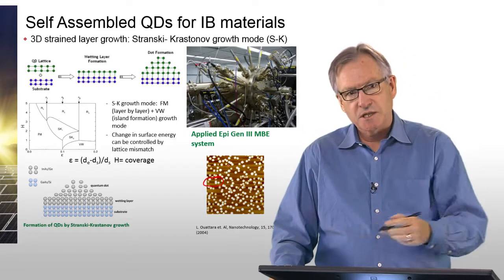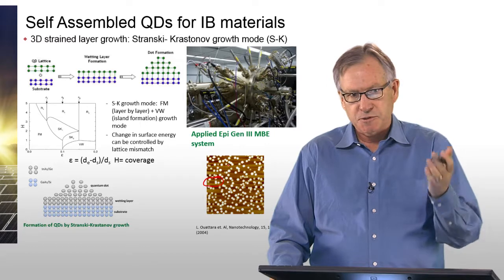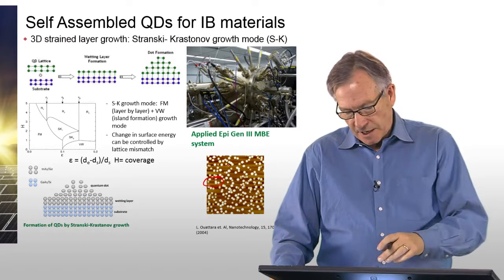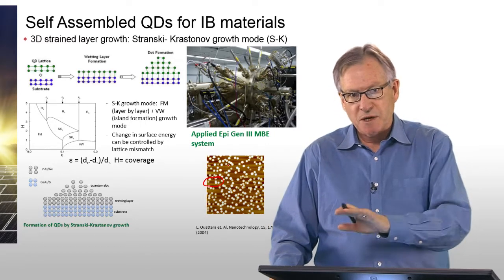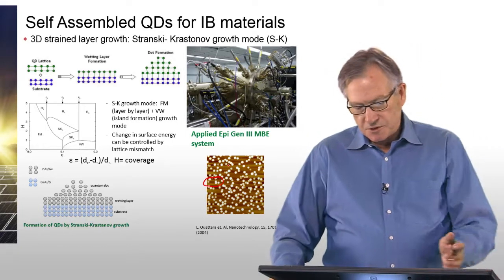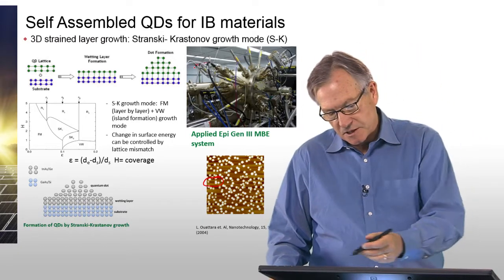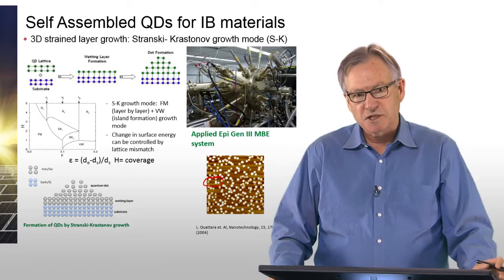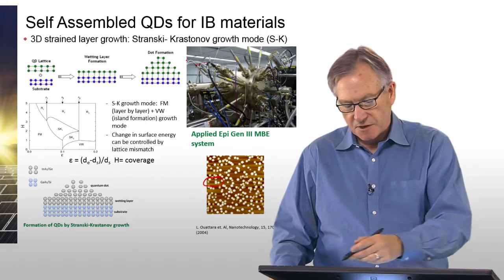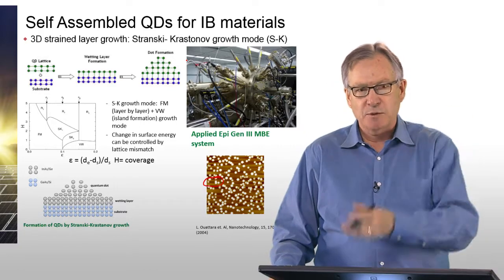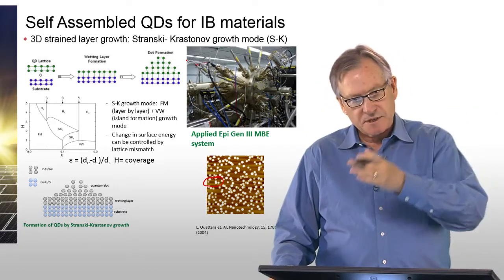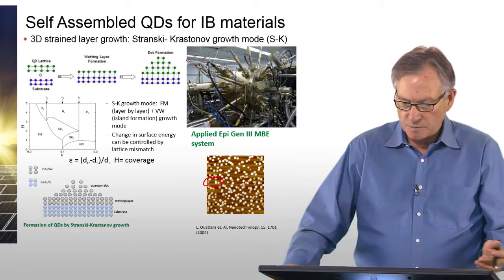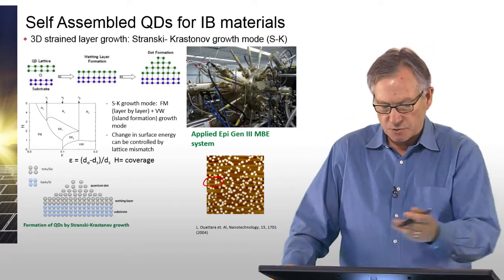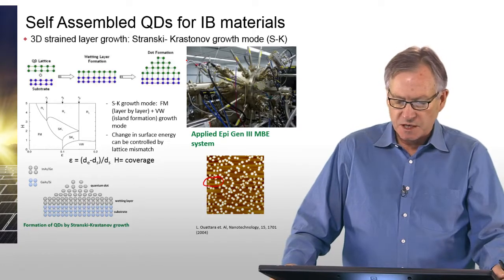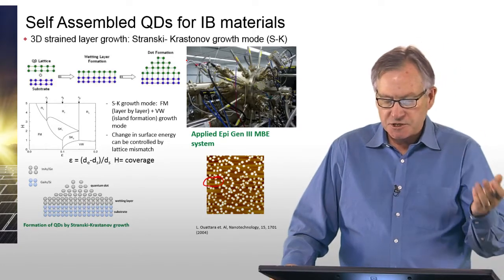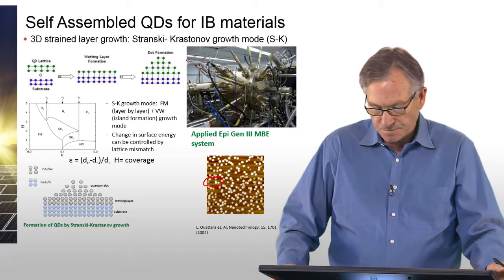And you can control the size by things like temperature, the flux of material, and of course, what type of material and what kind of strain you have present. So these are grown again using techniques like molecular beam epitaxy, which are relatively expensive. Molecular beam epitaxy is done in ultra-high vacuum. You start with a vacuum less than a vacuum of outer space, like 10 to the minus 11 torr, and then you basically co-evaporate these species in this ultra-high vacuum to form the layers. So this is how an implementation of intermediate band solar cells.